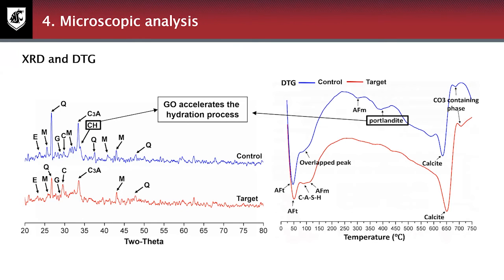Here we run the XRD and the DTG analysis. So from the XRD results, we detect some portlandite, the CH, in the control sample. The control sample means the geopolymer without GO. And we also find that CH disappeared in the target sample. This result was also confirmed by the DTG results. So combining these two results, we can summarize that graphene oxide accelerates the hydration process. That means the hydration in the target sample is much faster than that in the control sample, and that means more portlandite was consumed.